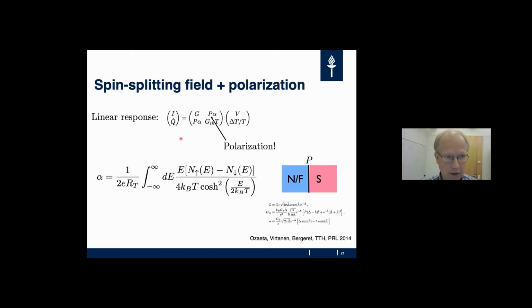Here, what you only need is the spin polarization of tunneling and the spin splitting of the density of states, and you get a large thermoelectric coefficient, which you can also study analytically in a certain low temperature limit.